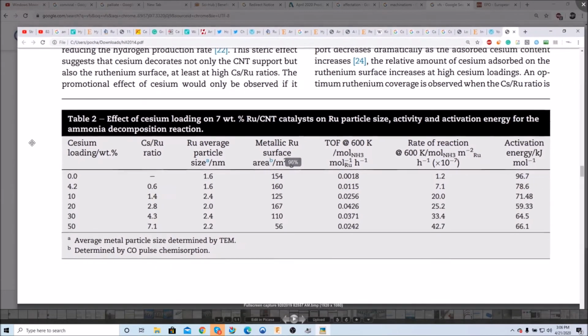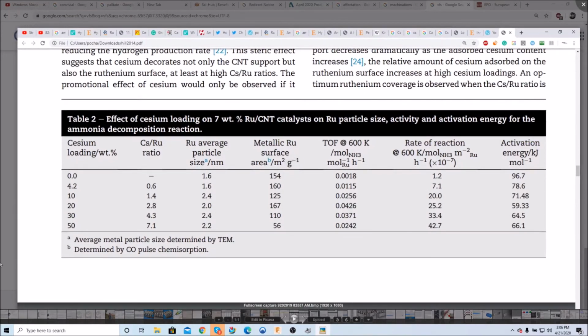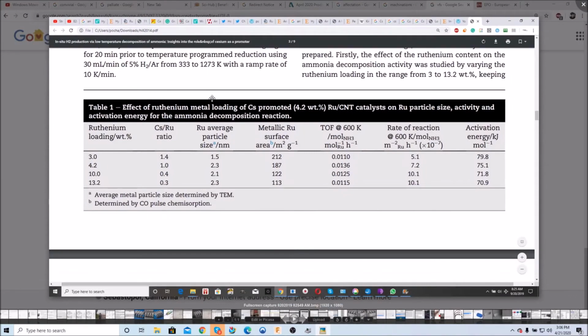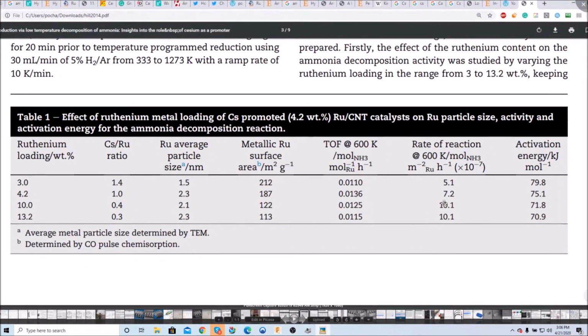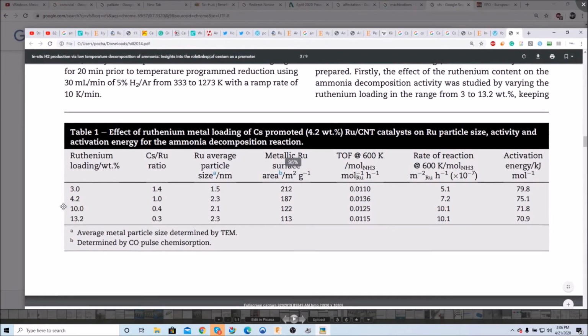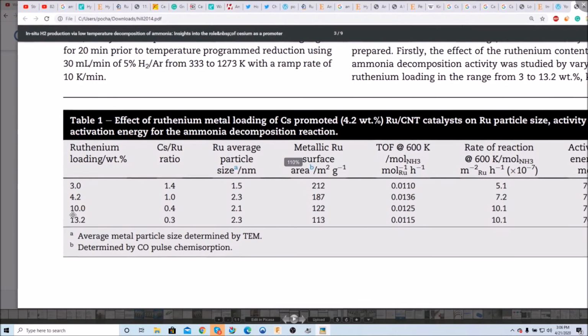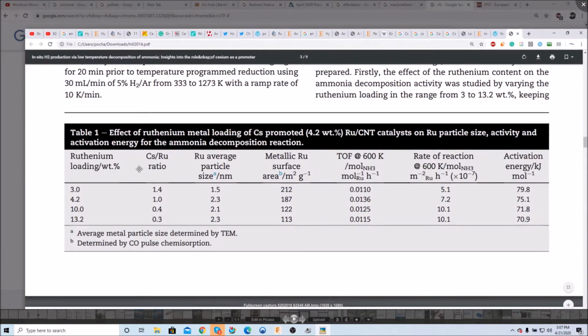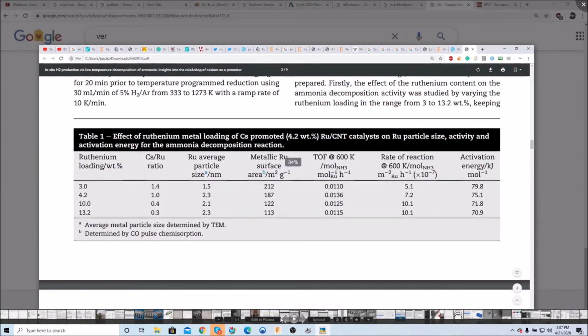This is one of the most important pieces of data. It shows the cesium loading and the rate of reaction. So rate of reaction increases sharply with higher cesium loadings. Now, if we move to ruthenium loading, we don't get nearly as sharp an increase in the rate of reaction. So we can have a 4% loading and our reaction is 70% as much as 10% loading.